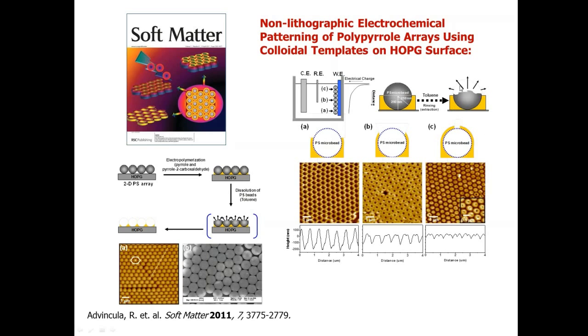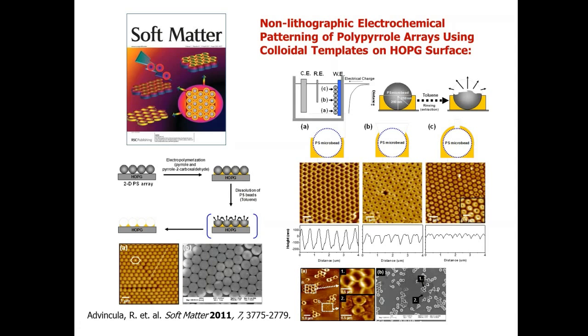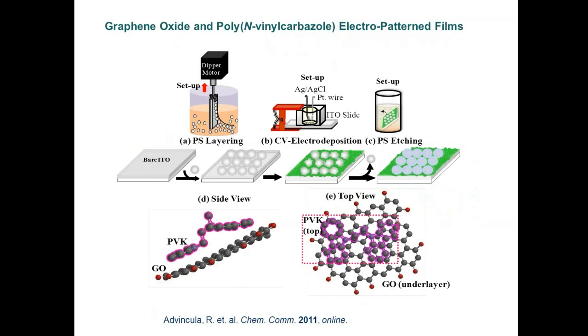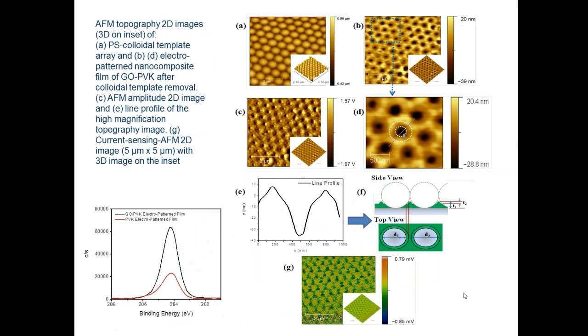By removing the templated polystyrene, we end up with a honeycomb structure. We end up with a half dome and full dome structure as well. This simply means that we can take any electrodeposition method and template them using these particles. So indeed, we did that with PVK polymer and the graphene oxide. We deposited them around these colloidal particles to produce a pattern which looks like this. What you are seeing here is a conductive form of the PVK graphene oxide complex that was deposited electrochemically around these colloidal spheres to produce this honeycomb structure.